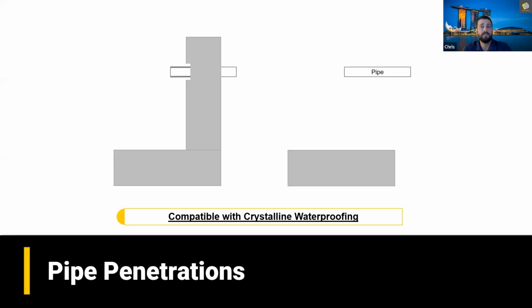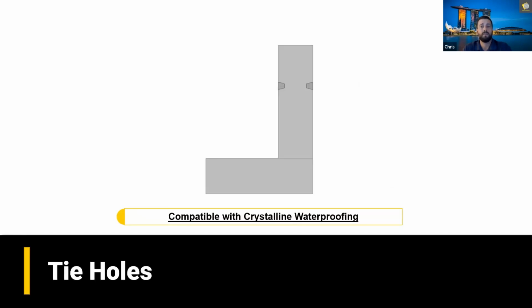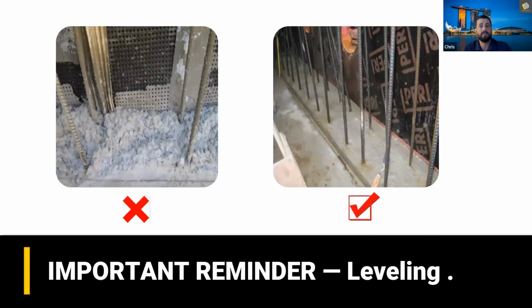For pipe penetrations, there are 2 options as well: external grout method or internal swellable water stop around the penetration before the concrete is poured. Of course, we can't forget about the tie holes. So if access is available to the exterior, a non-shrink crystalline grout is installed on both sides of the wall. An important reminder is to ensure that the substrate is properly prepared to receive a water stop. We see far too many construction joints like this that will require some chiseling, and this can be addressed early on in the pre-construction meeting.